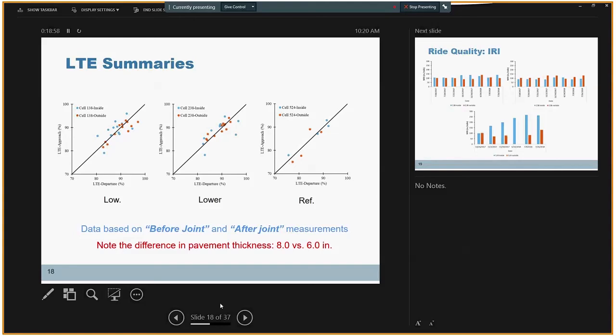And the graph on the right side of this slide presents the data we have for the reference cell. The LTE values are slightly lower, starting from somewhere like 75% up to 93-94% LTE for the departure and approach traffic. However, we should note that cell number 524, the reference pavement, had a thickness of 6 inch compared to 8 inch thickness for experimental sections 138 and 238.